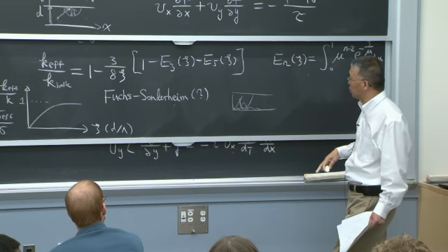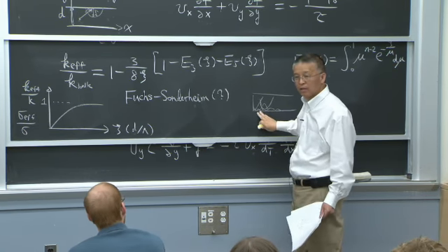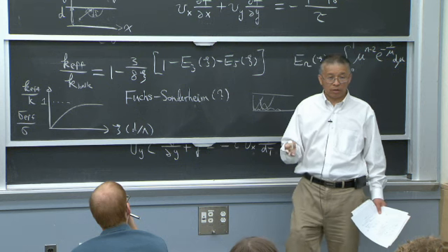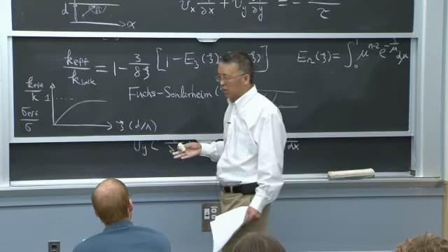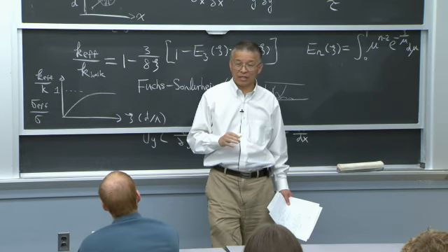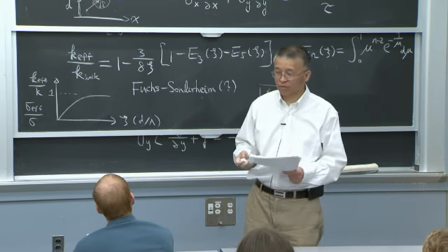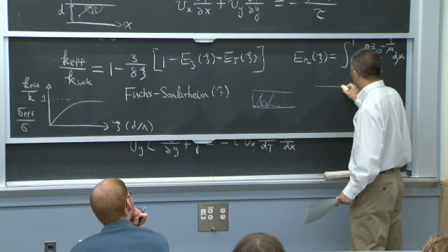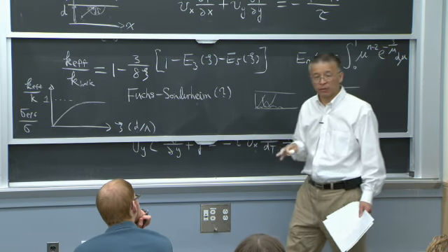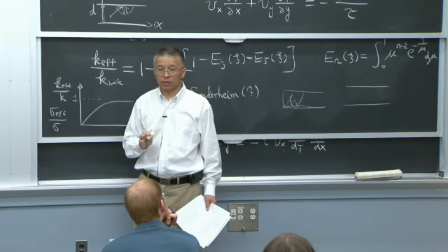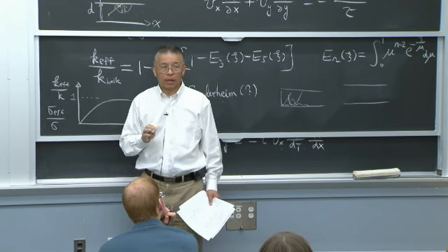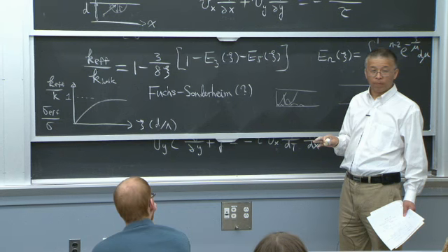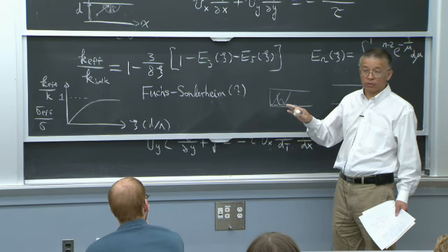In this case, what you measure is not just the surface effects but the interface effects also, because the grain interfaces are scattering centers. So you can't always say it's an effect that happens only at the surface; the interface also matters. And the other comment is, if you have a specular surface, you can again solve the equation, but the boundary condition changes. In this case, the specular surface does not degrade your transport. The ratio approaches 1.